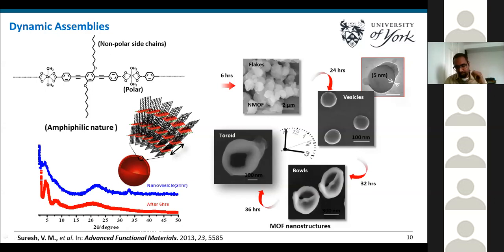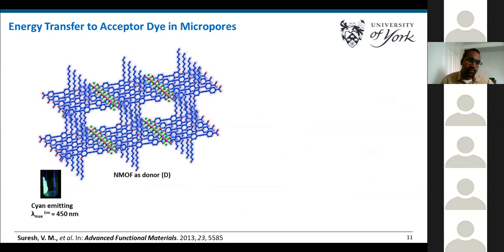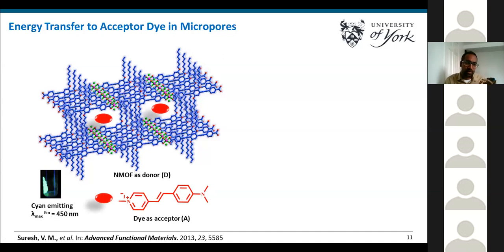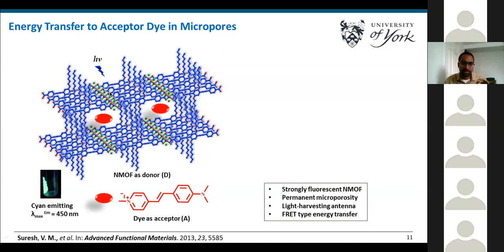So now we wanted to see its light emission properties. We have a supramolecular porous structure, which is strongly fluorescent because of the linker emission, and the emission maximum is around 450 to 460 nanometer. Now, we wanted to study its energy transfer and color emission tunability. So we doped it with a red-emitting dye. When we shine light on this MOF, the energy can be transferred over the MOF and finally transferred to the acceptor. And ultimately, we see the emission from the acceptor, not from the MOF.